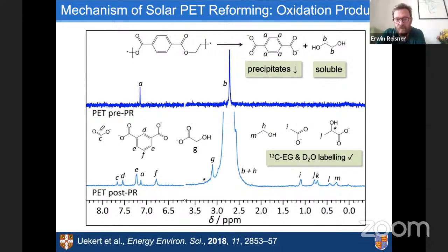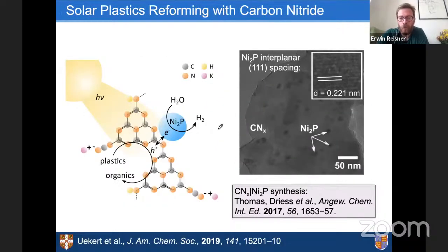And you can see the system works and we can extract all the hydrogen, but unfortunately the organic products are still a mess. So of course, ideally we would like to have a clean conversion into one interesting product selectively. Also here we moved on. So instead of using the carbon nitrides I've shown before, now instead of using this quite fragile molecular catalyst, we found following a work by Thomas and Driess here that you can also deposit nickel phosphide.